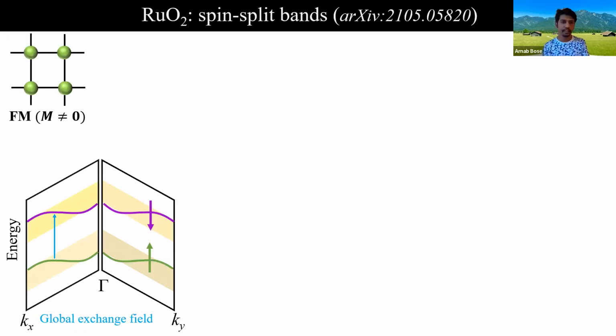Before jumping to the experimental results, let me discuss the band structure of ruthenium dioxide. First, let's start with the simple case of a ferromagnet, where we have non-zero magnetization. For the ferromagnet, we have magnetic ordering and a global exchange field that creates the spin split bands, as shown here. So this is well standard.